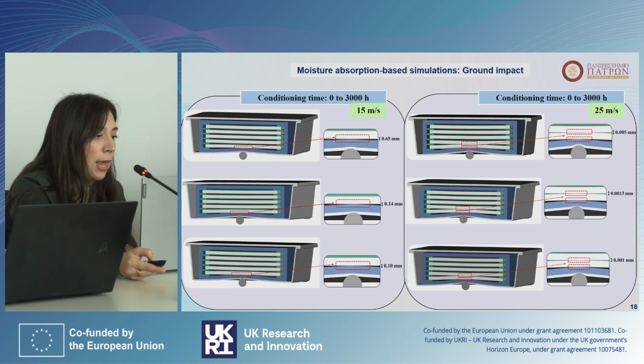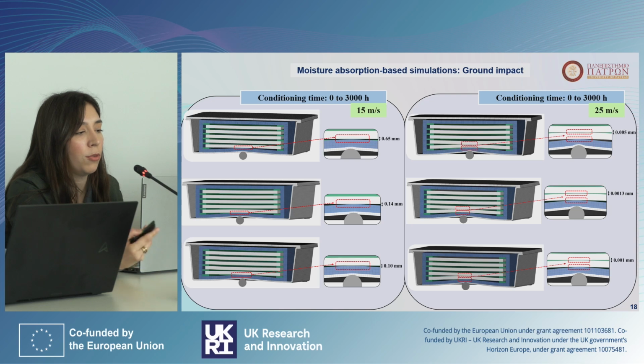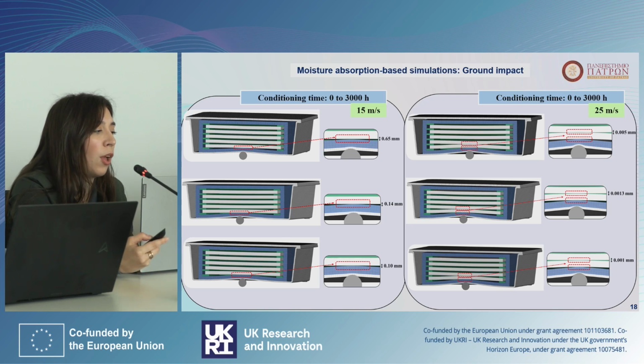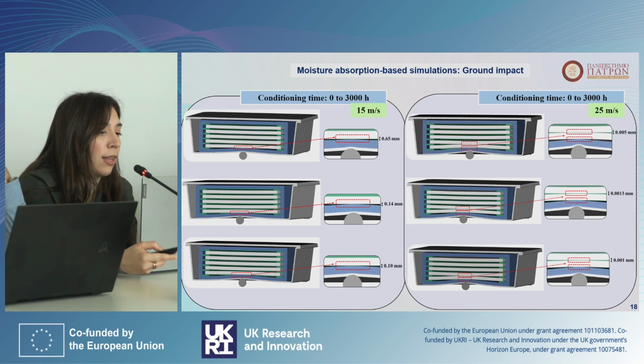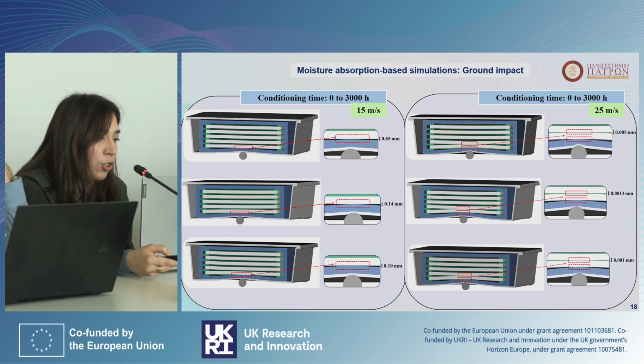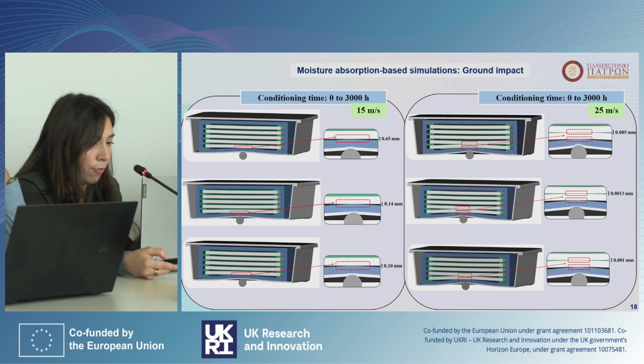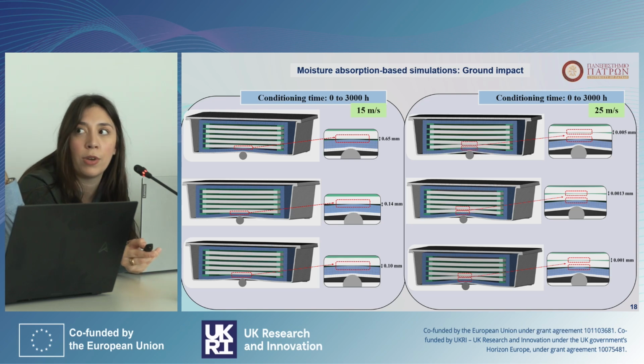Now we're moving on to modeling and simulation, and once the degradation models were validated at specimen level, they were implemented into previously validated impact simulations. This allows us to evaluate how environmental aging affects structural performance during ground impact scenarios. For instance, here, we can observe that the difference between the dry state response of the housing with the cell pack gets progressively worse from the dry state to the saturation state.